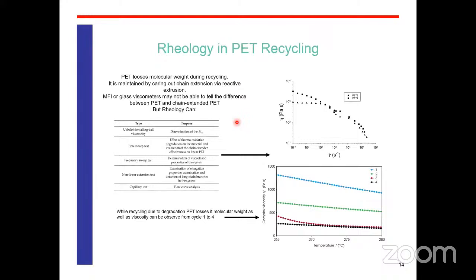This is all the data from the single cycle analysis. When you give it 4 cycles, your viscosity is going to reduce. For PET, polyethylene terephthalate, as I told you earlier, the more the thermal cycles, the more the degradation of polyesters, and the more the degradation, your viscosity will go down. These data are based on degradation. In the first cycle you get a higher viscosity, in the second cycle a moderate viscosity, then the third cycle, and in the fourth cycle the viscosity is quite low due to localized thermal degradation.